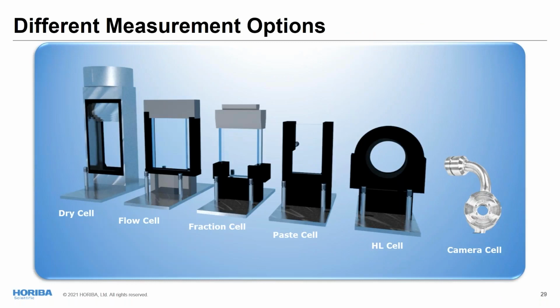But you also have different ways to disperse your sample, and that is mainly due to your sample properties. Some samples allow you to measure in different ways, some don't. So you can use a dry cell, which means you're not using a liquid for dispersion, you're dispersing in air. Or the flow cell, which is the one we use. Or we can use a fraction cell, which has a very small volume, about 5 or 10 mL of liquid. Pharmaceuticals have very precious samples, with a very limited amount of sample.